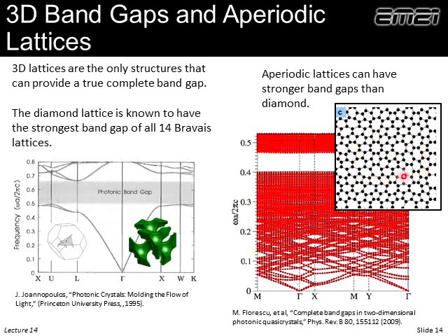And why does it beat it? It's because here the Brillouin zone, we have to account for the statistics of this, and the Brillouin zone, as it turns out, gets a little bit blurred, and that gives it effectively more symmetry. So the Bragg grating looks more similar in each of the directions due to the randomness, and it turns out we get a wide band gap. So these are the widest known, strongest band gaps. The other thing that amazes me is that the band gap occurs at such a high order band. This is something like the 30th or 40th order of bands up here is where we get the band gap. That's very surprising to me.